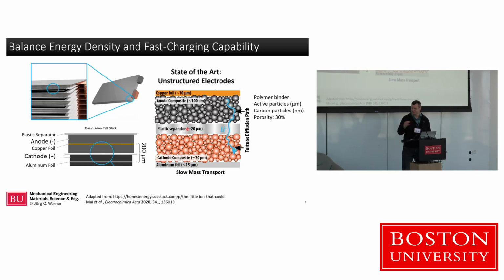And your separator, therefore, is usually also porous, so that liquid imbibes that porous plastic separator as well, so your ions can actually get all the way from one side to the other. Now, the way we typically do that these days in industrial applications is we literally just paint this onto the metal foils. We often compress it. So the porosity you have between these particles is very tortuous, pretty small, which is something you often want to have, because the fewer pores you have, the more material you can put in there, the more energy you can store. At the same time, the fewer pores you have, the more tortuous they are, the harder for those ions to move back and forth.